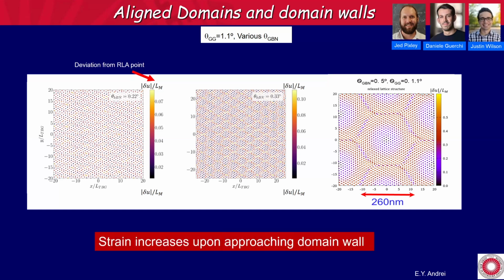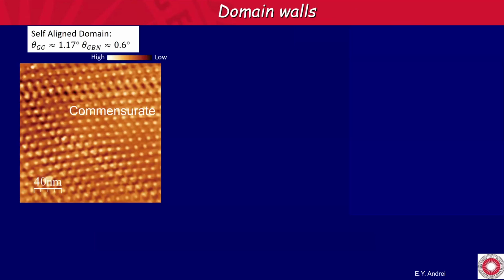Now, do we see this experimentally? So here we have a commensurate lattice, the 1-to-1 commensurate lattice. And just to make this clearer, I'm highlighting a domain boundary. Now in blue, this one here is a tensile boundary, where you stretch, where the displacement is perpendicular to the boundary.